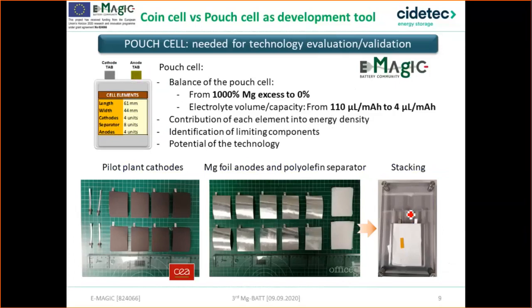Like, for example, at coin cell level, the balance of the cell is usually ignored. The excess of magnesium anode can reach 1000% at coin cell level, where the objective is to reduce it as much as possible in real prototypes. With the electrolyte volume, it's similar, and at coin cell level, we can reach very high values, above 100 microliters per milliampere hour. And to demonstrate the technology, we need to reduce it as much as possible. As a reference, 4 microliters per milliampere hour is given in lithium-ion batteries.